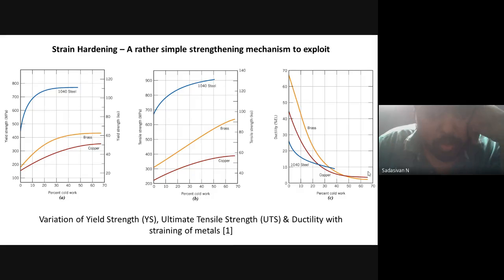So these are some plots of what happens to a material when I make it undergo plastic deformation. Let us take an FCC metal. If I process copper to some plastic range, some 10 percent of cold work, I get a significant enhancement in the yield strength and tensile strength, but it is accompanied with a drop in ductility. That is an undeniable fact. We lose some ductility for that. So it depends on what our application is. We can tailor make materials with required properties. We can take a metal and make it stronger.